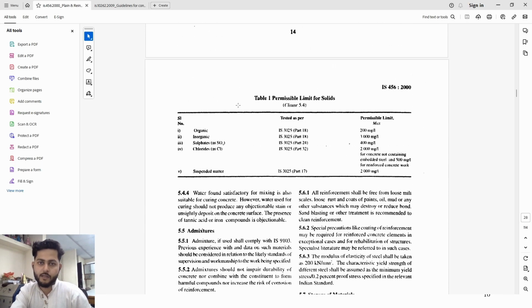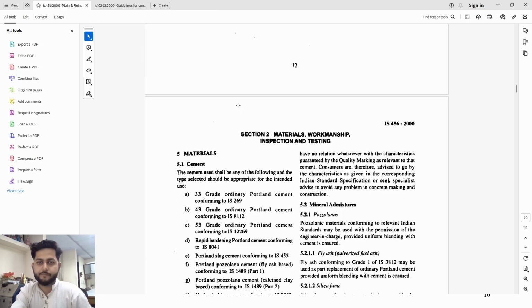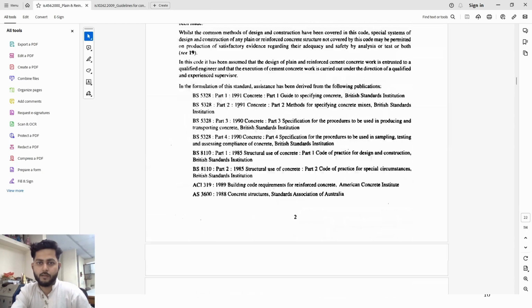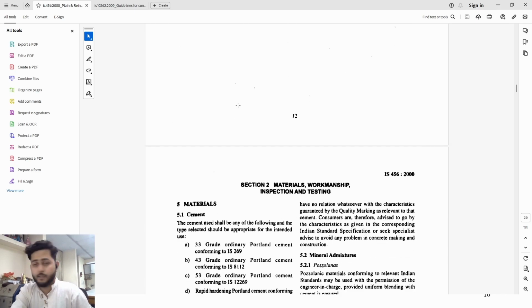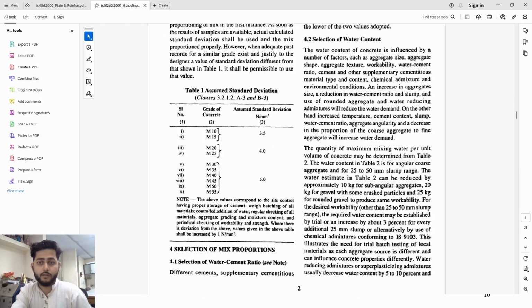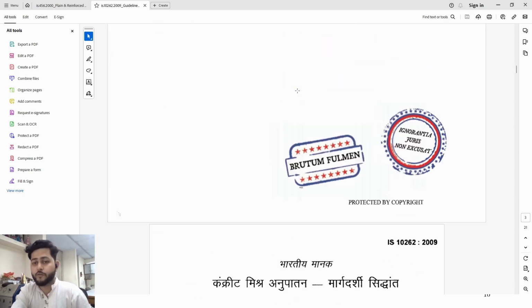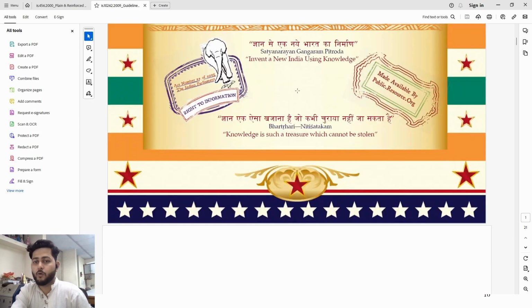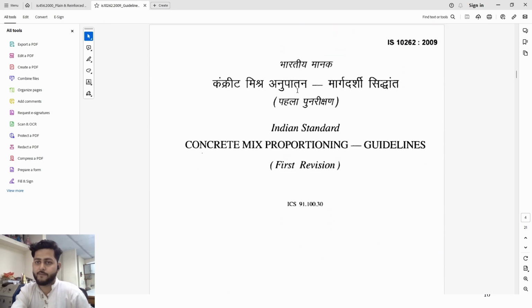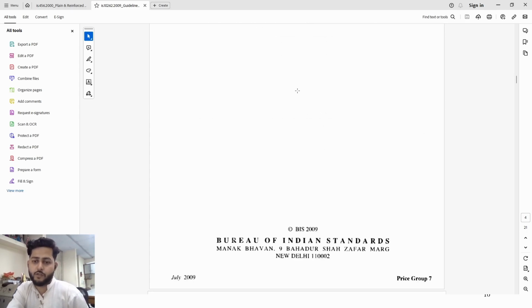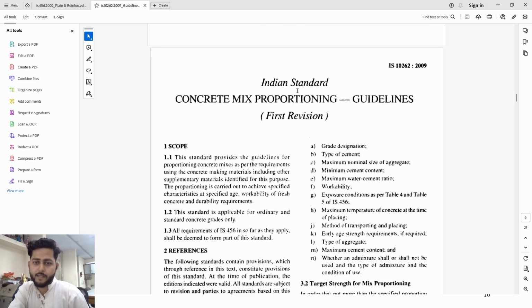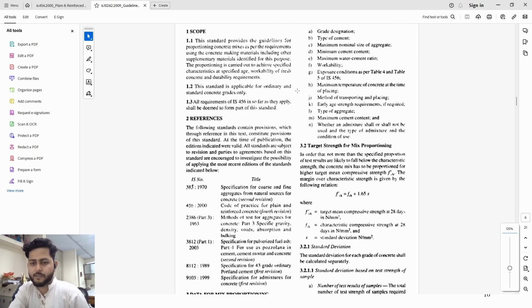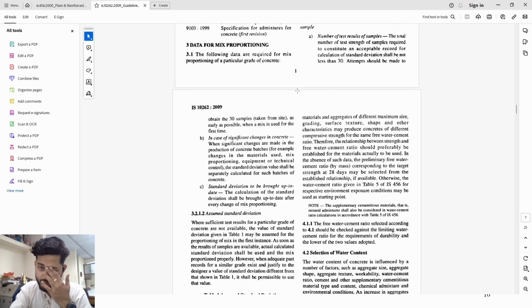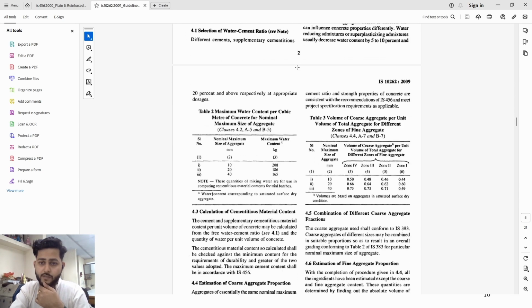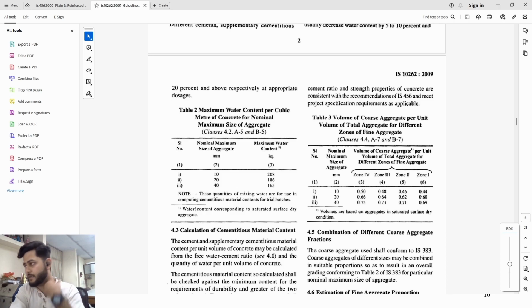So from the Indian Standard Code, IS 456, we can first calculate the C by A ratio, not this one. Yeah, this is from the mix design code, IS 10262 2009, and I have the 2009 version of it. If you have the 2019 version, the newer one, you can also use that. But this value is the same in the new standard as well. In order to decide the volume of coarse aggregate, you have to go to table 3 of the Indian Standard IS 10262.